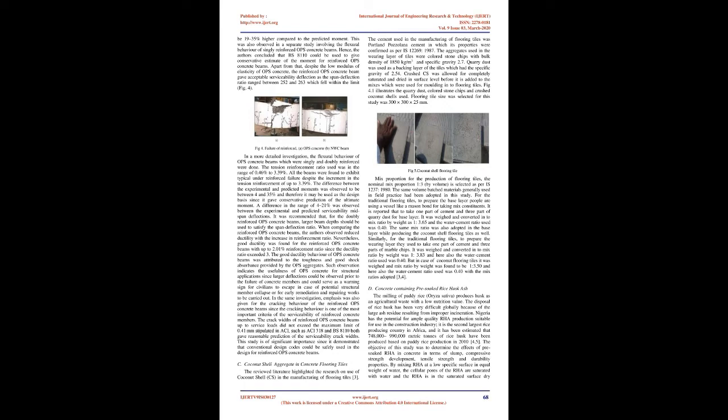In the same investigation, emphasis was also given to the cracking behavior of the reinforced OPS concrete beam since the cracking behavior is one of the most important criteria of the serviceability of reinforced concrete members. The crack widths of reinforced OPS concrete beams up to service loads did not exceed the maximum limit of 0.41 mm stipulated in codes such as ACI 318, and BS 8110 both gave reasonable prediction of the serviceability crack widths. This study is of significant importance since it demonstrated that conventional design codes could be safely used in the design of reinforced OPS concrete beams.